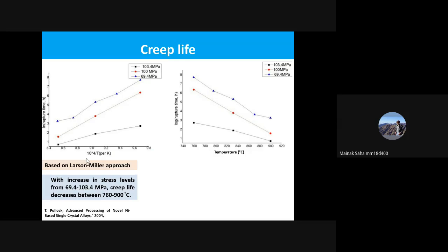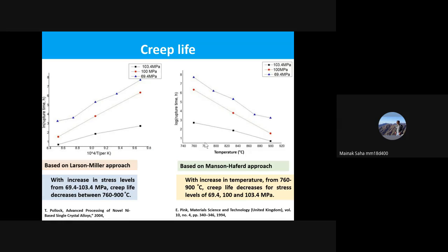Right? And then the other approach is the Manson-Haferd approach. Here again, what we can say is that with an increase in temperature from 760 degrees to 900 degrees, the creep life decreases for stress levels of 69.4, and as you can very clearly see, 100 MPa and 103 MPa. So we now have some indication of the creep life as well.